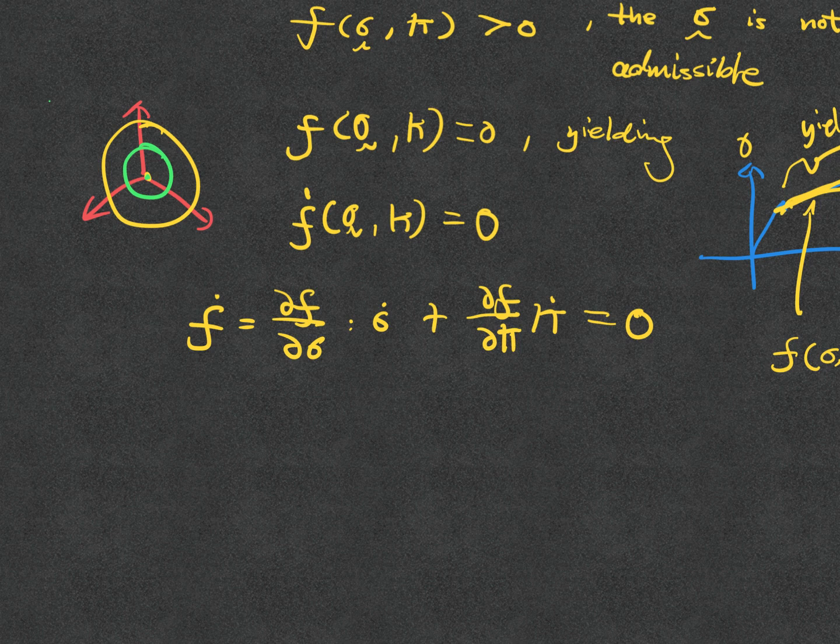Okay, so they share. So what it actually means is that if the material starts yielding here, and I move from here to this point, the yield surface needs to grow accordingly so that it remains touching the arrow. Okay, do you understand what I'm saying? So this part is the change of the radius. This part is the stress arrow that is evolving in the stress path. Okay, you get what I'm saying?